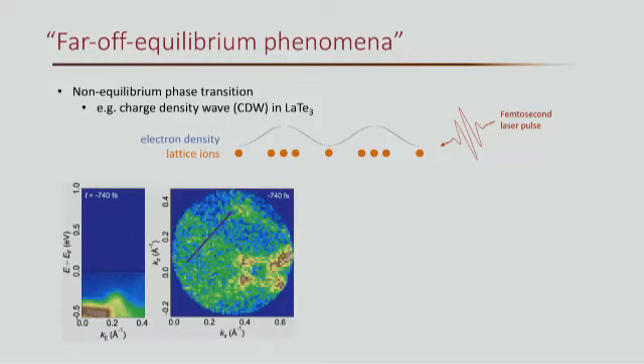So here is a preview of what I'm going to talk about later. But without getting into too much experimental detail, here's the first movie I want to show, which is basically a measured ARPES spectrum. On the right-hand side, you're seeing the Fermi surface map of this particular charge density wave material, lanthanum tritelluride, which is a prototypical example of a one-dimensional charge density wave.